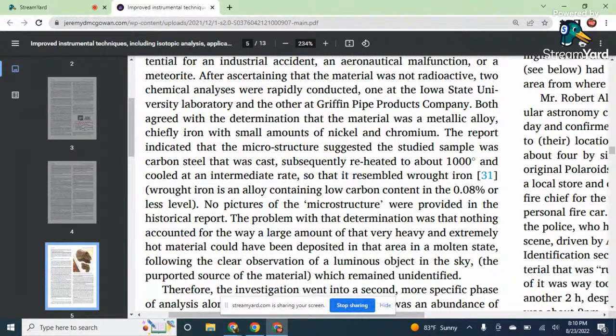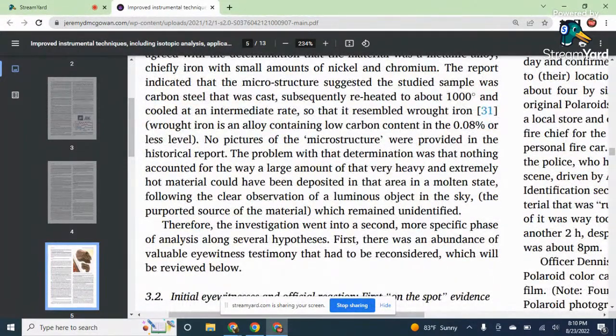The report indicated that the microstructure, so the microscopic structure, very small scale structure, suggested the study sample was carbon steel that was cast, subsequently reheated at about 1,000 degrees and cooled at an intermediate rate, so that it resembled wrought iron. So wrought iron is an alloy containing low carbon content in about 0.08% or less level. So wrought iron contains very low amounts of carbon, less than 1%. So it's like 0.08%, a fraction of a percentage. No pictures of the microstructure were provided in the historical report.